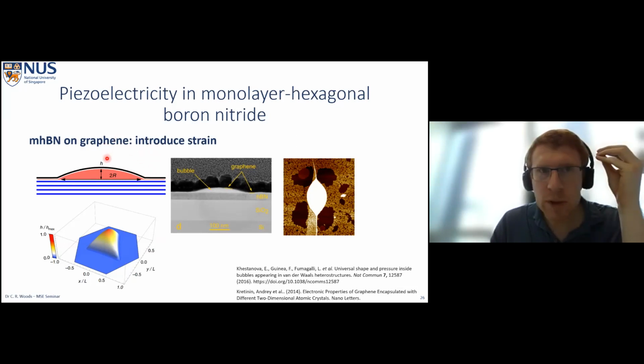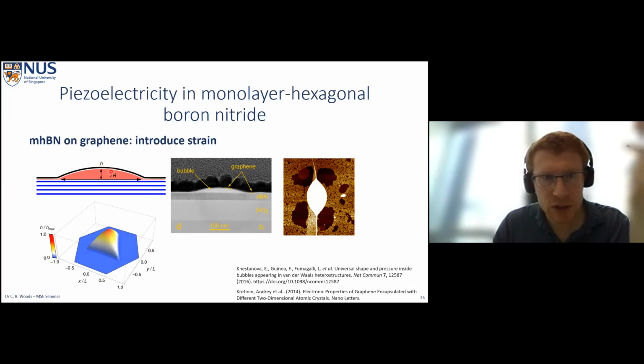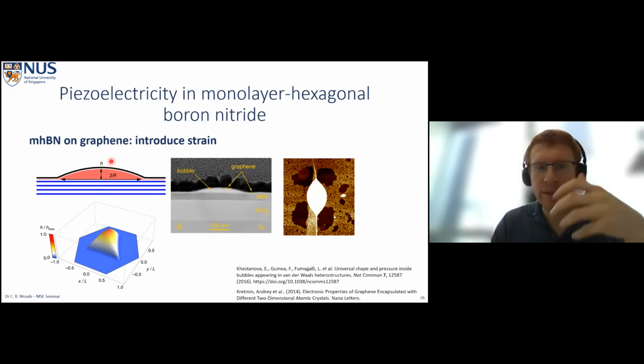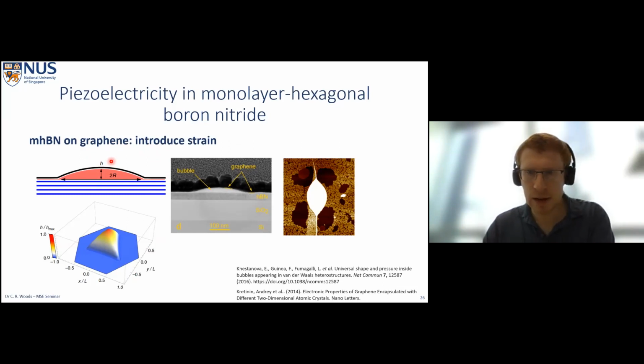One of the problems with our electric force microscopy measurements is that if you tried to measure, say, the effect of piezoelectricity on top of the bubble, you would have to decouple a lot of different signals. You have topography changes across here. You also have unknown materials and distributions within this bubble. But what we know from the bubbles is that they have this strain distribution around the edge. And here, there's no topography at all, really. This is where we get these atomically smooth areas. So it's a system where we've already decoupled the topography from the strain. You might also consider introducing strain using nanopillars or other techniques like that. But they have the same problem, where you would need to decouple some nanopillar topography signal from your electric force microscopy signal. But the bubbles we knew were an inbuilt system where we already had this decoupling.